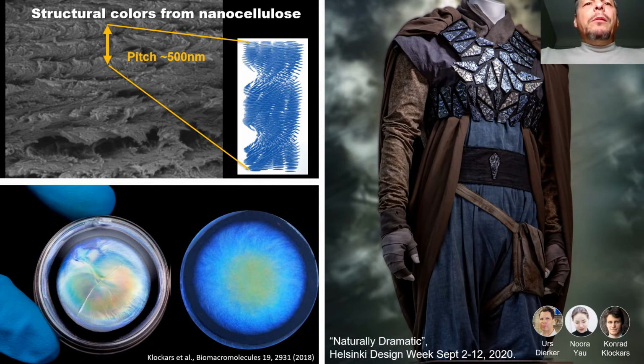This can be further developed into, for instance, developing color. And this is a fact that is very well known for cellulosic nanomaterials, in particular cellulose nanocrystals, that in suspension form this type of arrangement called chiral nematic liquid crystals. And when a suspension of those crystals is dry, then the system is collapsed into a film that produces selective light reflection with very interesting colors and effects such as iridescence. So this is also illustrated on the right.